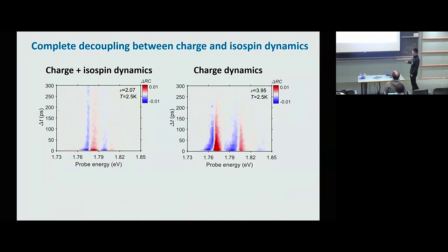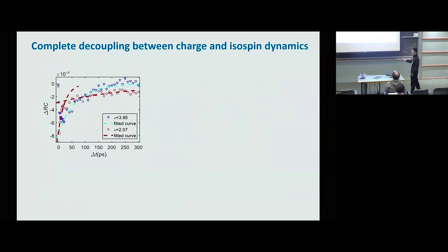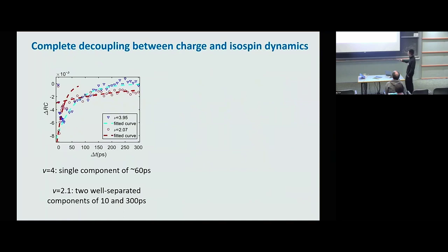So supposedly we should be able to directly see their decoupling in our measurement. And indeed, we can see their decoupling directly. So here we are seeing a full dynamics at around minus 2 filling and around 4 filling. So at a glimpse, we can probably already tell that this dynamics looks qualitatively different. But it's more clear if we just compare their decay dynamics directly. So here the blue symbols are at 4 filling, and we can see that it's very well described by a single component with about 60 picosecond lifetime. But if you look at around 2 filling, given by the red symbols, then apparently it cannot be described by a single decay component. There are 2 well-separated components, with 10 picoseconds for the fast component and 300 picoseconds for the slow component, respectively.